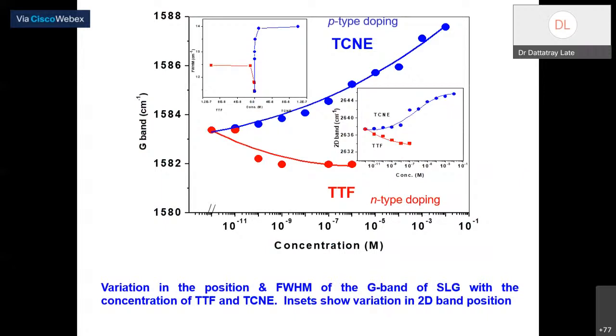What I find, okay, let me go on increasing the concentration of these molecules, either TCNE or TTF, and I have monitored the G band position. In graphene, the G band is highly sensitive to strain effects. Small changes on the graphene surface immediately show up in the spectra. You see, without any concentration, and when I started adding the concentration, for example, here I started at 10 raised to minus 11, and increased.